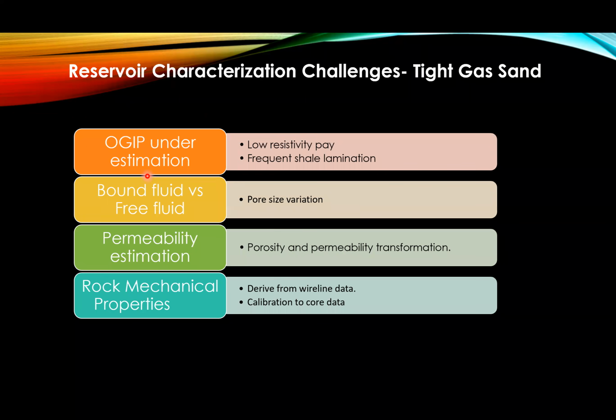And as I mentioned, pore size variations. Pore size variations drive your permeability and also your bound fluid versus free fluid, right? If you have smaller pores, that means larger areas to be covered by the first invading fluid, that is water mostly, so you have larger water saturations, but that water will not produce because it is bound to the surface of the grains, and with extremely small pores there is much larger surface area. That's why bound versus free fluid is an important parameter here.